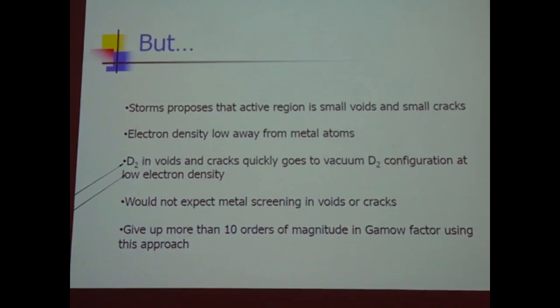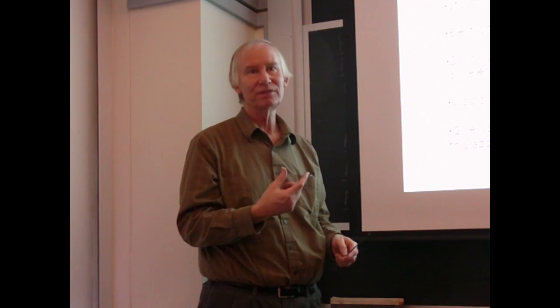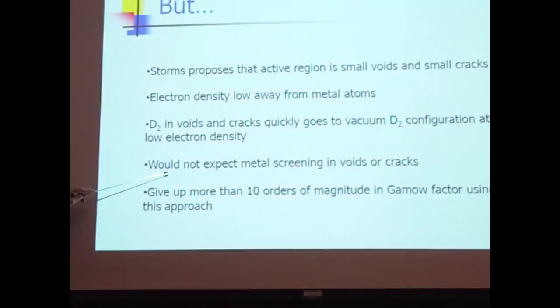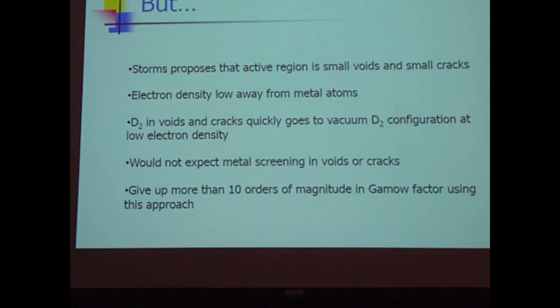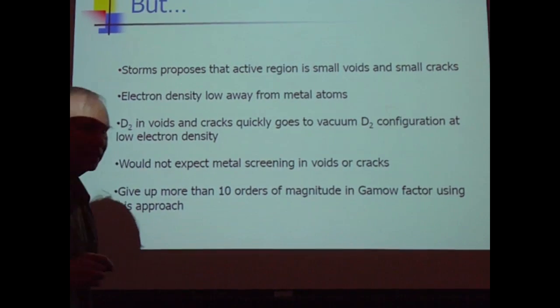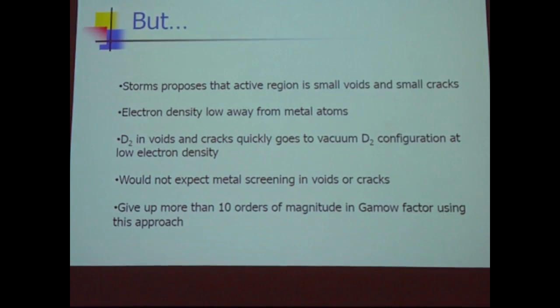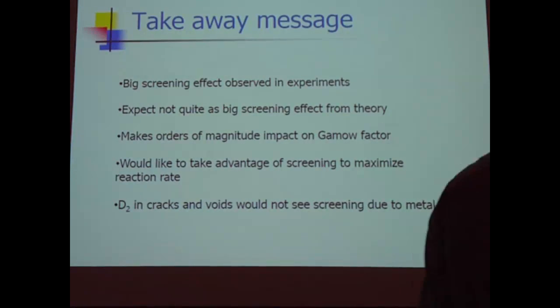So if your molecule looks like a molecule and it's away from the metal, you've got no screening, which means you would expect to see the molecular screening number. You'd expect to see 25, 27 volts for the screening energy in this case. And because you don't get the metal screening away from the surfaces in these small voids or cracks, you're giving up more than 10 orders of magnitude in the Gamow factor using this approach. So I'm of the opinion that you really do want and need the high electron density and having the metal atoms nearby to do your screening.